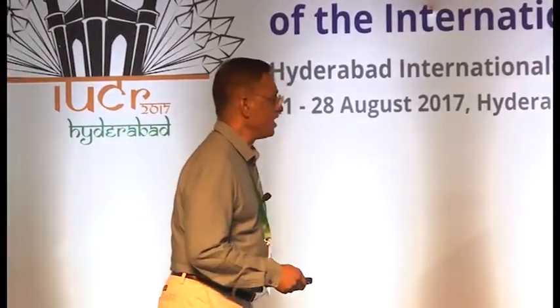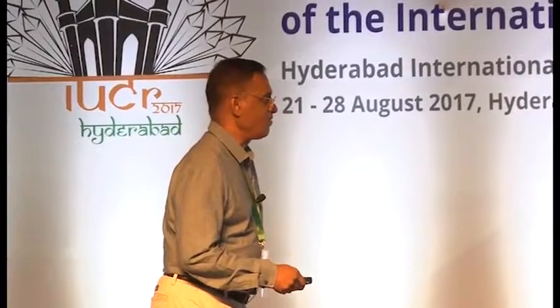When we tried to do the refinement in Cc, again, the Flack parameter was very close to 0.5, maybe sometimes 0.6 or 0.55, 0.75. But the thermal parameters were not really very good. But this is experimental evidence that we know that this particular compound shows SHG. Because of that, it has to be non-centrosymmetric.